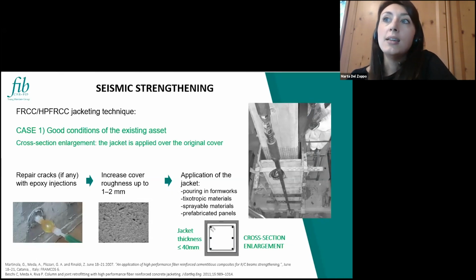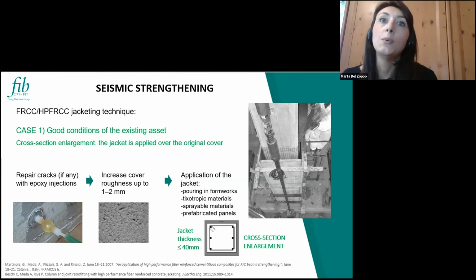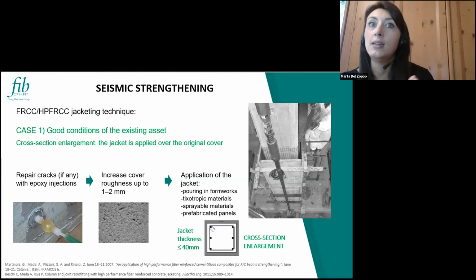Let's now see how the jacketing with the FRCC actually works. So first of all, we need to understand which is the actual condition of the asset that we want to strengthen. If the substrate of the member that we want to strengthen is in good condition, in this case we can apply the jacket over the existing, original concrete cover, and in this way we are doing a sort of cross-section enlargement of the element. So of course, first of all, we need to clean the surface and repair, if there are, for example, cracks, hairline cracks, with epoxy injection or mortars. And we need to increase the roughness of the surface because we need to ensure a good bond between the existing concrete cover and the new material, the jacket.